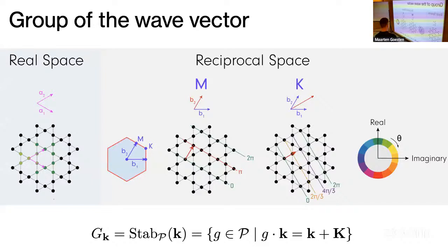Now, again, this is a simple picture of how to derive the crystal orbitals from a basis. If we look at the crystal lattice, what we're taking here is the Kagome lattice, and the reciprocal space, the Brillouin zone, looks the same, but is rotated by 30 degrees. What you obtain is that the full point group of the lattice, the group of the wave vector, is D6h at gamma, and here becomes D2h at M and D3h at K.